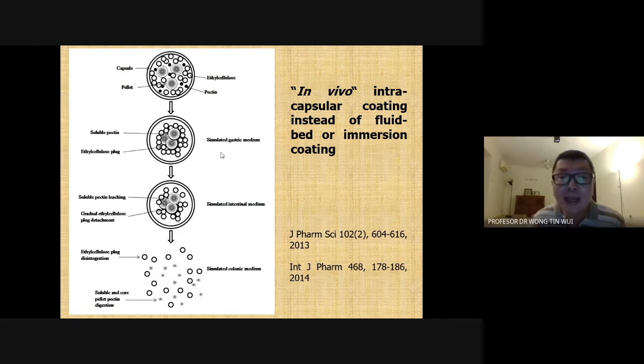or the biological fluid will enter into the capsule and wet the pectin. Once the pectin turns soluble, it becomes adhesive and sticky. Now, it will stick the hydrophobic ethyl cellulose together with the pellets and form a very robust and hydrophobic plaque. Now, this plaque is very robust and resists disintegration and dissolution of the drug in the gastric region and small intestine. So as a result, we can prevent premature drug release, and the majority of the drug is released in the colonic region. This is because in the colon, we have a lot of microbial enzymes released from the microorganisms.